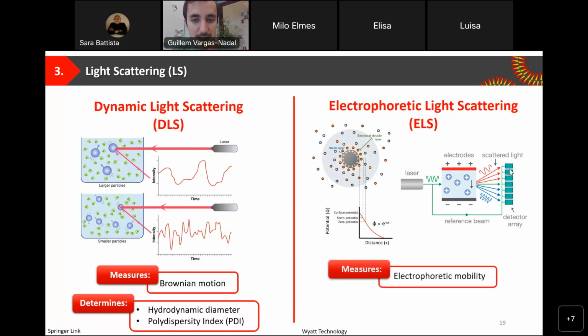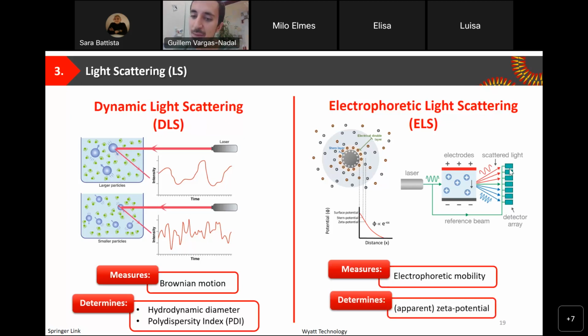And it is important that this technique measures the electrophoretic mobility. With some equations and approximations, we determine the zeta potential, or in brackets, the apparent zeta potential, in case we are not using the correct approximation or the correct equation. So it is important to keep in mind that ELS measures the electrophoretic mobility, and with that we determine the zeta potential or the apparent zeta potential.